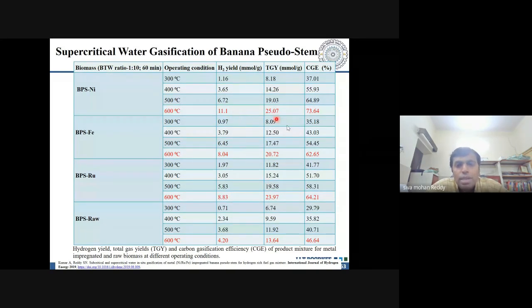Not only the hydrogen gas yields, but you also see that the total gas yield has been significantly improved, right? So the total gas yield in the presence of your nickel is going to be almost doubled, and the carbon gasification efficiency, which was around 46, has been improved to 73 in case of nickel, whereas for iron it is 62.65, and for ruthenium it was around 64%.